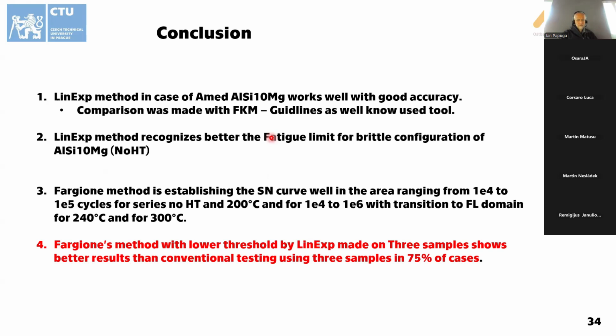I think with the Fargione method combined with the lower threshold, we were able to mimic or predict the SN curve quite well in all of the cases, except the no HT series, where there were some problems, I think, with the data scatter, so that's quite problematic. And the huge claim out of this presentation is that out of all the cases that we tested, in 75% of the permutations, we were better by using the self-heating methodology presented in this work compared to only 3 samples used for conventional testing.